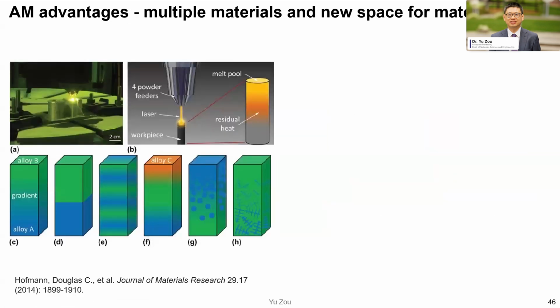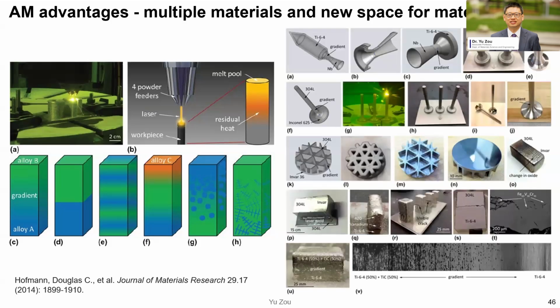Okay. Another big advantage of the DED method is that in the printing process, we can change material because there are a few nozzles. This is a very nice review paper that talks about making compositional gradient materials. For example, we can have alloy A and alloy B, and then there's a gradient between alloy A and alloy B, and then we can tune the composition and microstructure during this process. So this provides a good opportunity to design new materials. So DED additive manufacturing is not only about making a part, but also making new material.